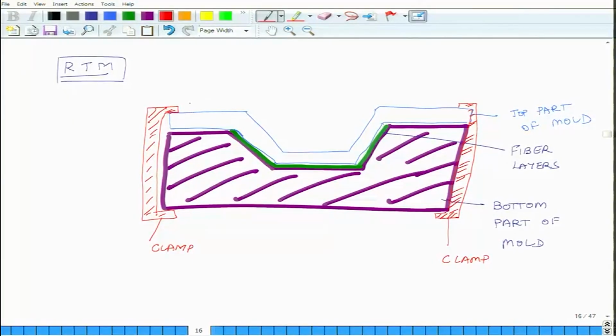And of course, from the top part we have, there is some gap between the bottom and the top and there is air in there. So, we have an outlet for air and this we connect to vacuum. But we have still not shown how the matrix gets added, and this is where, so the matrix is injected in this mold once all the layers have been put through some outlet. So, this may be the path for matrix material, resin. So, resin is injected and it is injected at a pressure,